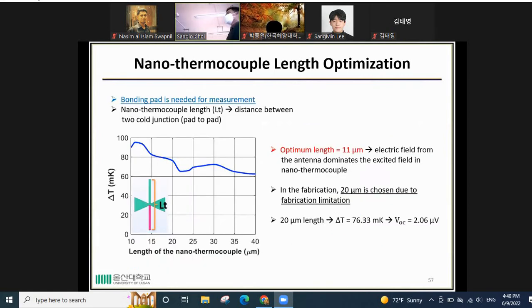And also for measurement, we use a bonding pad. That's why we need to optimize the nanothermocouple length also to achieve maximum temperature difference and maximum output voltage. So this is the plot of the temperature difference as a function of the nanothermocouple line length, which is the distance between the first cold junction and second cold junction. From this, we can see that the optimum length is 11 micrometers.